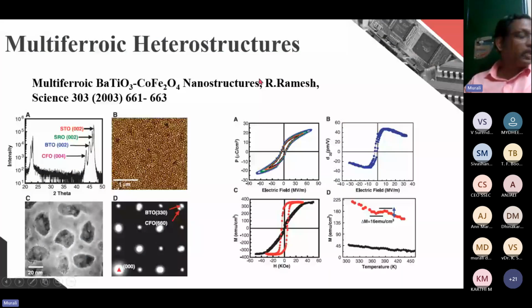So if you see on the top, this is the atomic force microscopy image. These are cobalt ferrite, which is a very good magnetic material, and the matrix is the ferroelectric material, barium titanate, which is the model ferroelectric material. Okay, so this is the XRD, the technical data. So this is the epitaxial thin film.